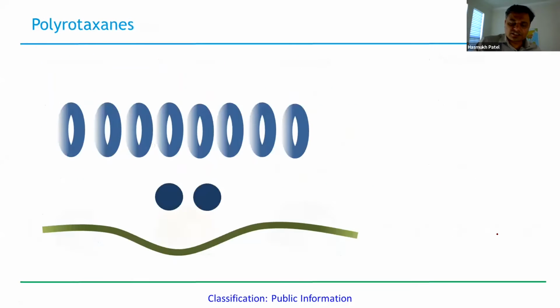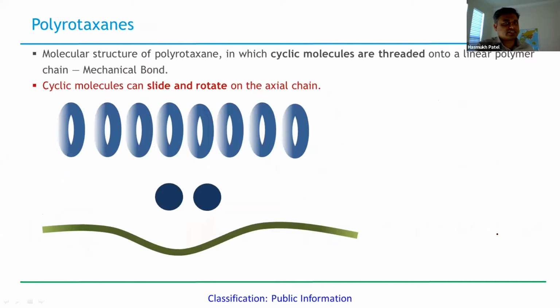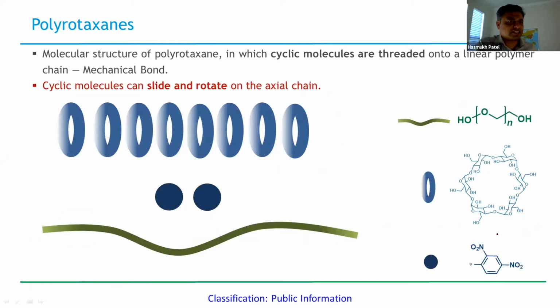So how can we make this Polyrotaxane? A Polyrotaxane is a molecular structure where the cyclic molecules are threaded onto linear polymer chains, and it forms mechanical bonds. The cyclic molecules can slide as well as rotate on the axial chains. As you can see, the green string is a polyethylene glycol, the cyclic molecule is an alpha cyclodextrin here, and we also use a capping agent, which is a nitrogen aromatic compound. How we can make it is a very simple process.